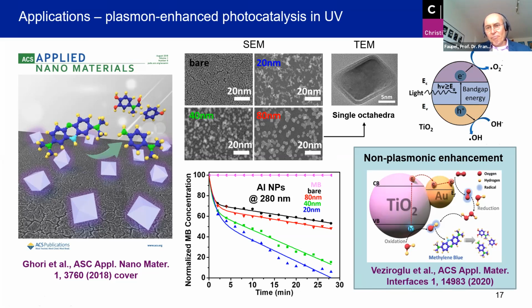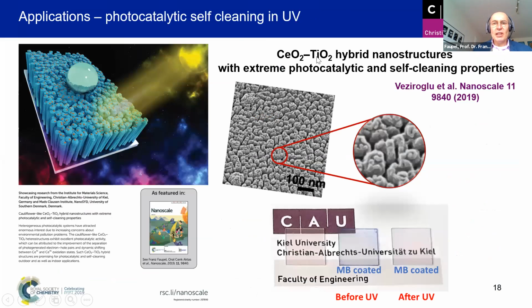And we also went a step further. Instead of only using metallic trapping centers, we use hybrid oxide structures. For instance, we use titania in a columnar structure, especially designed for high photocatalytic activity. And then we deposit with the techniques I explained earlier, for instance, cerium oxide or other oxides. And these tiny spots here in this sketch are the cerium oxide particles. Here again, we take advantage of charge transfer, but in addition to charge transfer, we can prepare the particles to tailor the defect structure. So cerium 3+ and cerium 4+ defects here play a key role in enhancing, in addition to charge separation, the properties. And those coatings have excellent self-cleaning properties.